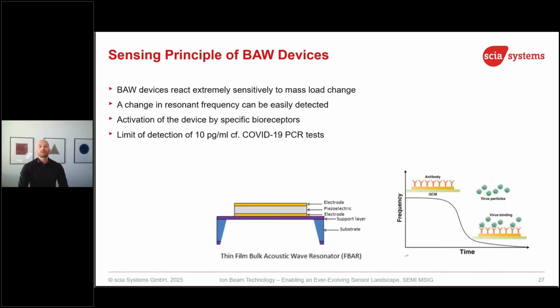Anyway, so in order to do biosensors, one can use so-called bulk acoustic wave resonators. So in that case, we see here a so-called FBAR, film bulk acoustic wave resonator, using the piezoelectric effect I just explained. So we have a piezoelectric material, aluminum nitride, with electrodes on top and bottom. And then you could apply a certain frequency, and the resonance frequency finally of your device depends, of course, on the mass of the device. Means if the mass is changing, frequency is changing, and frequency could be measured very easily. It's just counting, right? Frequency measurement. You can do it extremely precisely.